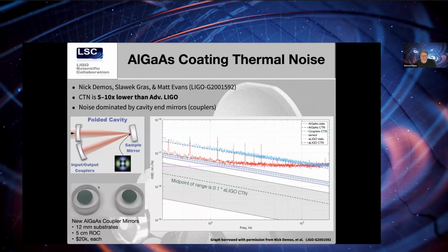We got AlGaAs coupler mirrors. These were very challenging to make, and because of their unique nature, quite expensive actually. So these just arrived earlier in the summer, and they're about 1/2 inch in diameter, 5 centimeter radius of curvature, and about $20,000 each. But we're hoping that by the end of the summer, we can have a direct measurement so we actually know how low we can drive the noise level with AlGaAs coatings.